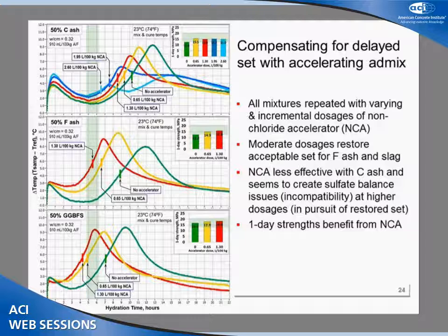again, we try different things. We vary the proportion of that non-chloride accelerator in replicate mixes to see where we need to be. For the F-ash mixtures, a pretty mild dosage rate, something on the order, this product I think ranges up to about 40 if you language you speak in dosage rate. This would be about 10 and about 20 ounces per hundredweight. It doesn't take too much to get us in the target band. And again, this improves our one-day strengths.